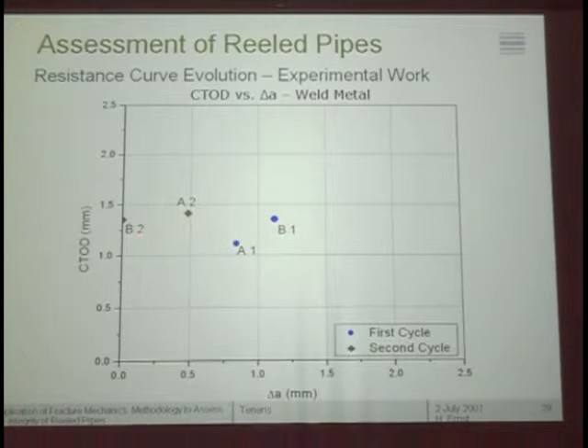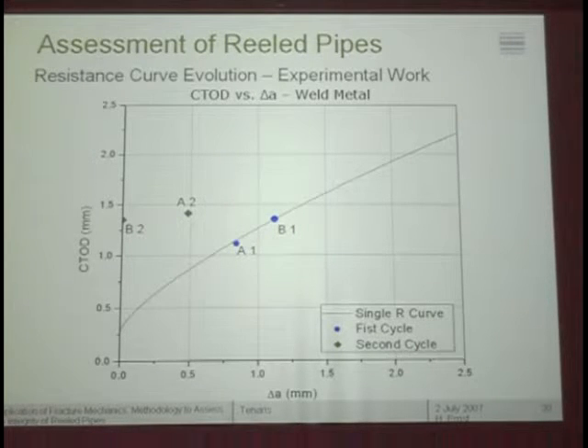And the same thing for B. Now, if you put on top of that the resistance curve that you got from multiple specimens, but we got only one cycle each time, then of course the curve goes through the first cycle crack extension levels, because the specimen didn't know that you were going to put another cycle. So this is okay. But what do you do with all this?